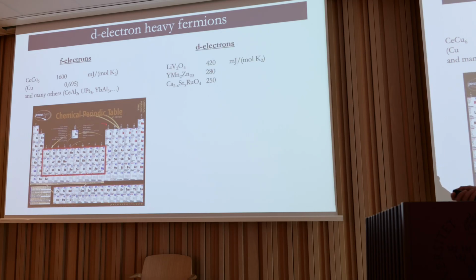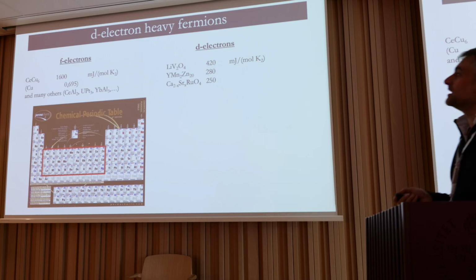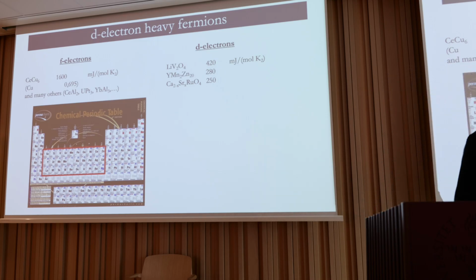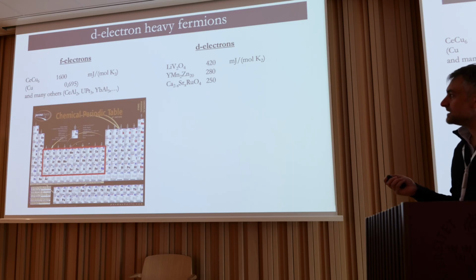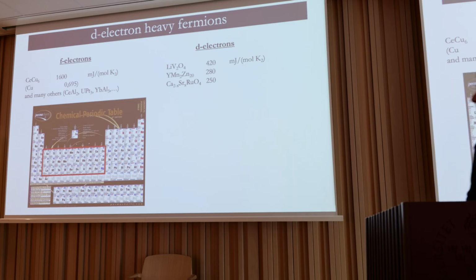Now, there are some heavy fermions known that do not have F electrons. The main one, the most known one, is lithium V2O4, which has an interesting Sommerfeld coefficient of 420 millijoule per mole Kelvin squared—I don't know why these two come down here. But then there is yttrium manganese 2 zinc 20, and there is some doped ruthenate, and these are done, of course, with d-electrons, so transition metals.